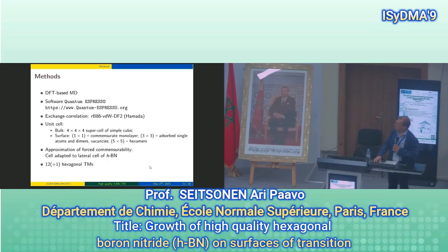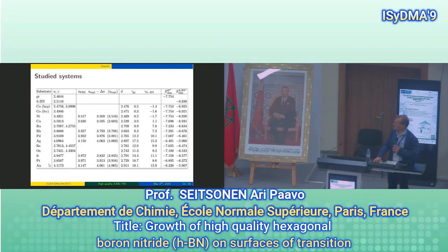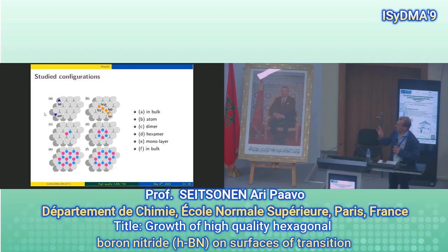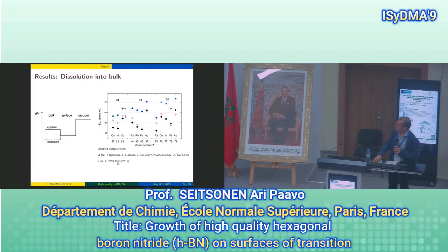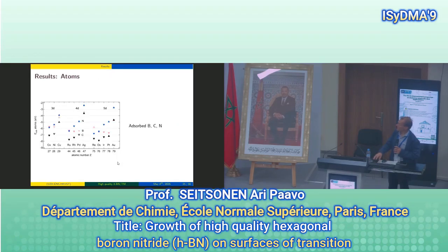So this is now the study that we did with Thomas. I said we calculated 12 substrates, these different adsorbents. And here is, for example, the mismatch between the two. This is the percentage mismatch of the lateral lattice constant of hBN or graphene and the substrate beneath. So those are the 12 cases plus one; we calculated two forms of cobalt. And then adsorbates: we had the atoms B and N in the bulk and on the surface, different positions, dimers, hexamers, and then the full monolayer and vacancy. But I have no time to go into this. Here are just some numbers of the adsorbed atoms and so on.